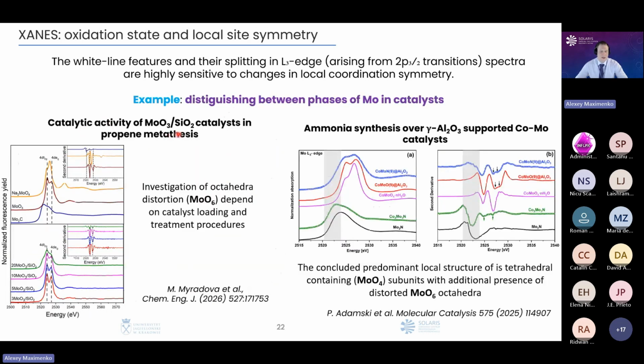And imagine that you have different types of catalysts. For example, one of them is octahedral and another is tetrahedral, and you would like to investigate what is going on with your catalysts during the chemical reaction. So you measure such a material before, after, or even during the reaction, and then by analysis of the splitting and the ratio of the first and the second peak, you could understand if changes in your catalyst appear, and if they appear, what kind of changes you have by analysis of the changing distortion of your material.